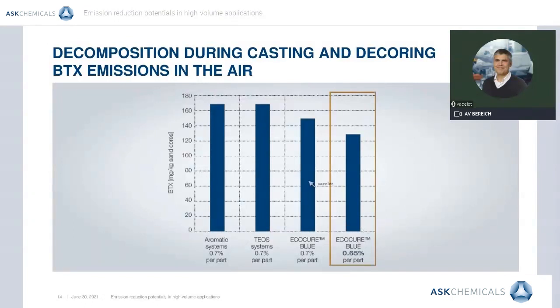So we can see that the selection of pure solvents and the reduction of monomer or aggressive additives can slightly reduce the BTX. But when the binder reactivity is optimal, we can often reduce the use of binder. And that has a much bigger influence on the reduction of BTX or other pollutants. We can see here that the reduction of only 7% of the binder can provoke a 13% reduction of BTX. And that is the key message. The less organic material you have in the sand at the pouring, the less BTX and other pollutants you will produce. And that is definitely the best way to reduce the emission.